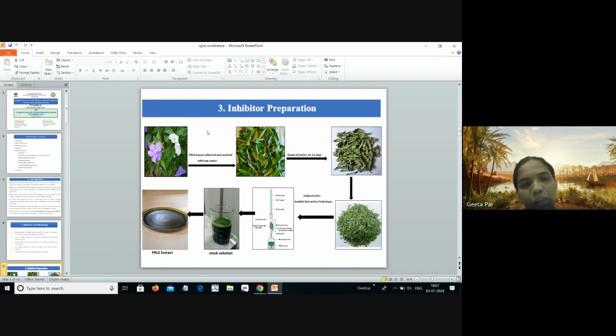Inhibitor preparation. The Putranjiva roxburghii leaves were collected from the Botanical Garden of Karnataka Science College, Dharwad. The leaves were shade dried for 15 days. Then they were pulverized into powder form. Then it was used for Soxhlet extraction technique, which is an effective technique for isolating primary and secondary metabolites from natural sources. Then it was used in a rotary evaporator. After the rotary evaporator, the crude extract was obtained in semi-solid form. Then the crude extract was used as an inhibitor for further studies.